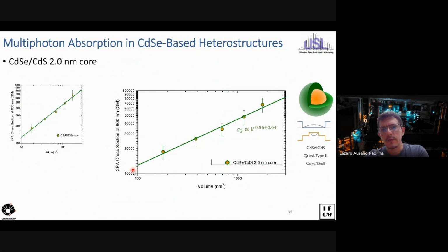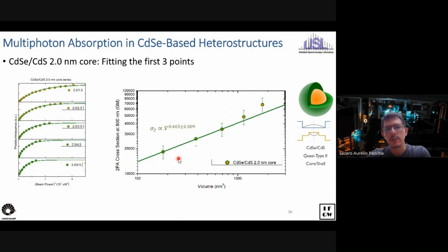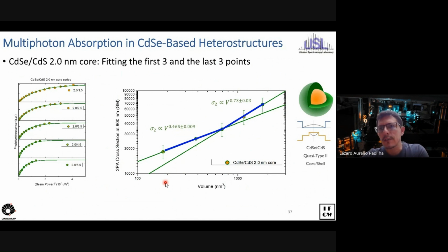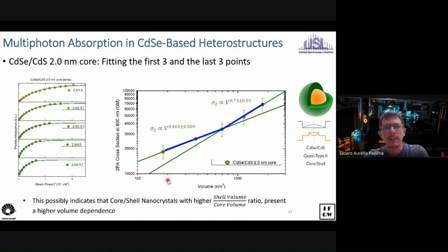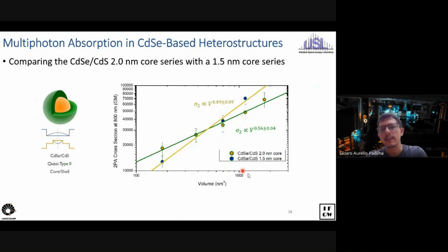And more than that, if you look closely at this data here, we can fit the volume dependence with a regular, single linear fit. However, if you look closer, you'll notice that if you fit just the first few points, you get a slightly smaller slope, and if you fit the last few points, you get a different slope. In fact, it suggests that the bigger the shell compared to the core, the steeper is this dependence. That could suggest that if you had a smaller core, you would have a higher volume dependence. To test that, we have studied a different set with a smaller core.